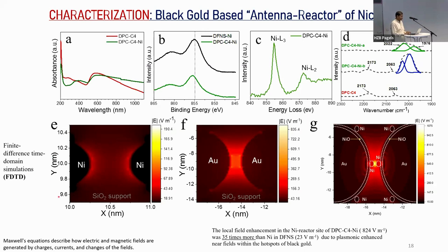Another interesting thing that happens in the plasmonic material is the polarizing electric field, right? Because of the surface plasmon resonance, we produce a huge polarizing electric field around these nanoparticles. And look at this particular field, which is around 824 volt per meter. Now imagine if your CO2 or any reactant is in that electrical hotspot, what will happen? That polarizing electric field will bend and stretch the CO2 molecule, and that allows you to reduce the activation energy further. So that's the additional benefit of using the plasmonic material over the semiconducting material.